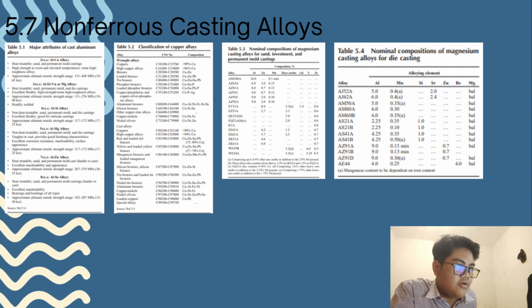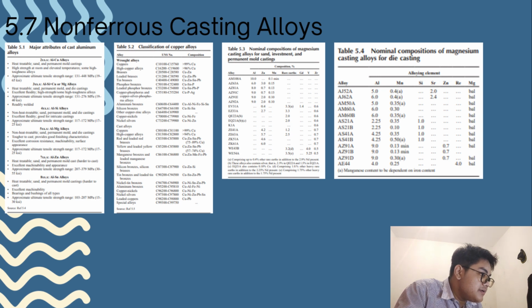4. Hydrogen is the only gas with appreciable solubility in aluminum and its alloys, and hydrogen solubility in aluminum can be readily controlled by precision methods. 5. Many aluminum alloys are relatively free from hot short cracking and tearing tendencies. 6. Chemical stability. And 7. Good as-cast surface finish with lustrous surfaces that suffer few or no blemishes. We can see several pictures here, Tables 5.1, 5.2, 5.3 and 5.4.